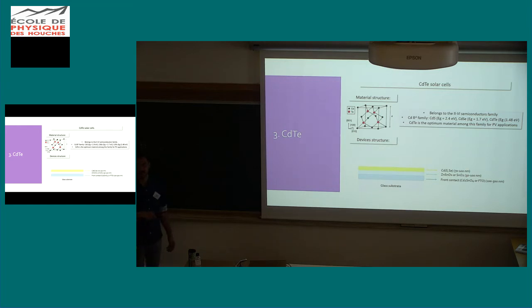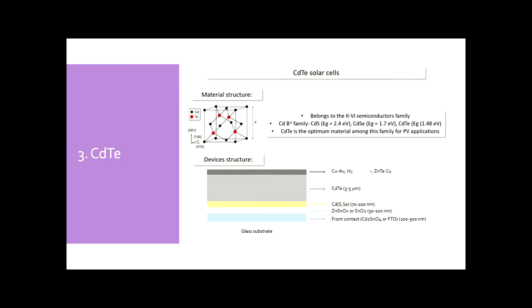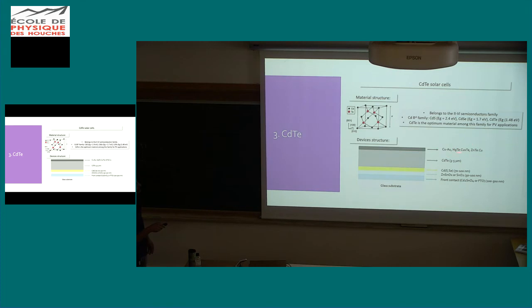Remember that we always work with P-type semiconductors as absorbers, because we are extremely good at making solar cells using a P-type absorber and then selective contacts for this P-type absorber, but extremely bad in the opposite way. And you deposit cadmium sulfide around 70 to 100 nanometers, and then the cadmium telluride absorber between 3 to 5 microns. Normally people right now are using 3 microns. And then you finish with the top contact. That used to be copper gold, or mercury telluride with copper telluride, or zinc telluride with copper. You have different choices because this is the most complicated part of the device. The work function of cadmium telluride is extremely high, so there are few materials that can really not block the current when you collect here.